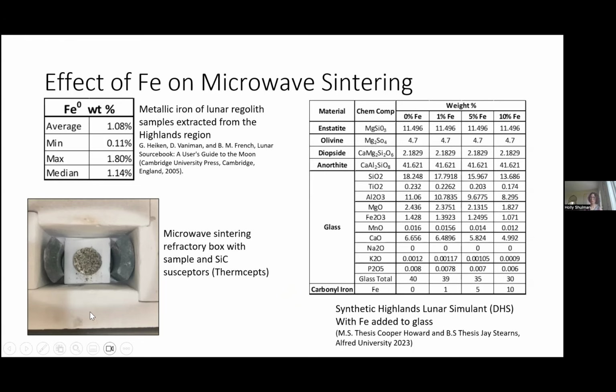And then on the left, this is showing the system, the package that we set up. I call them thermal packages. And this is a high temperature refractory. I know the dielectric properties of it. It handles very high temperatures, for safety, but also for microwave transparency, because we're shooting microwaves right through this. And then we have some silicon carbide susceptors, which are actually a composite that I developed. I call them Thermcepts. So it's got a proprietary composition, and they're just really great for microwave processing. And then the sample is sitting here. And we have a 2-color optical pyrometer that we can sight on that sample directly, and we can also sight on the susceptor. So that's our setup.